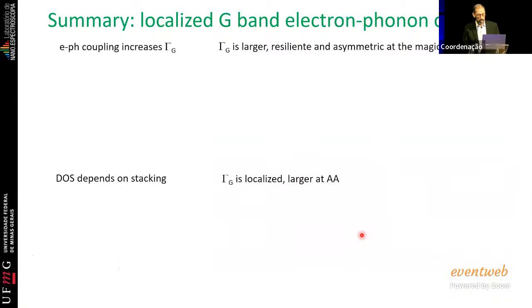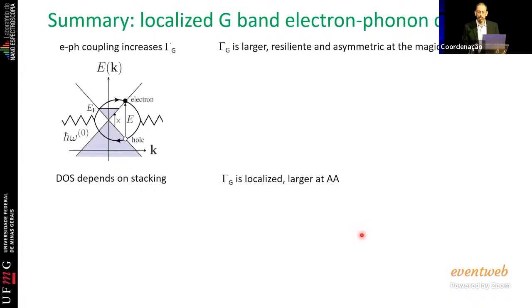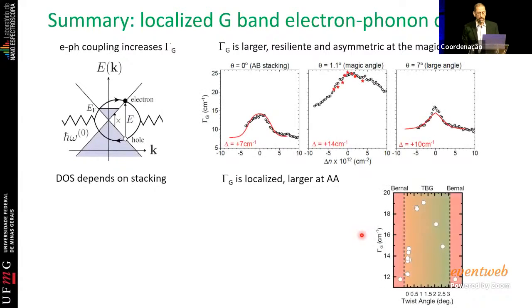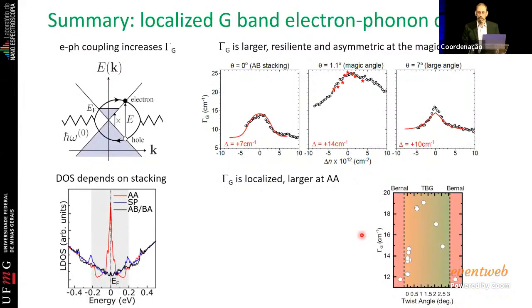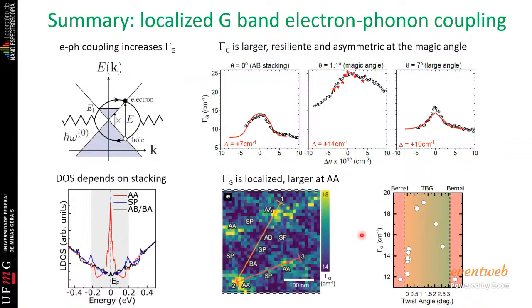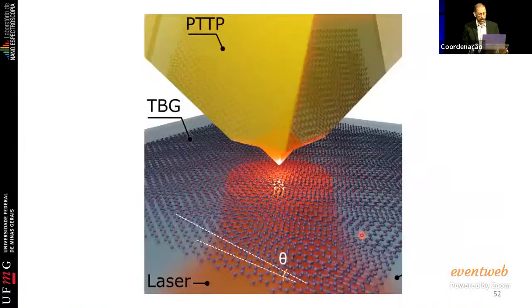structure. So summarizing, we have this strong electron-phonon coupling in graphene. We see that this is special in the magic angle, and we see that all these effects are actually spatially localized. And I will skip those just to say that the next step is a lot about nano optics. The field generated by such an antenna is not really homogeneous, it is very structured. And this is what we are working out to understand.